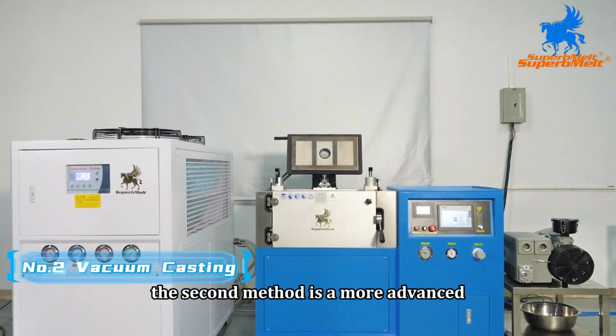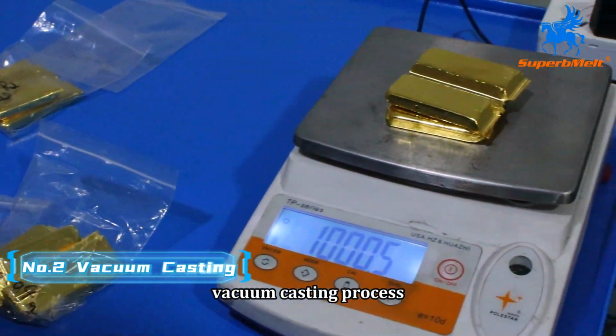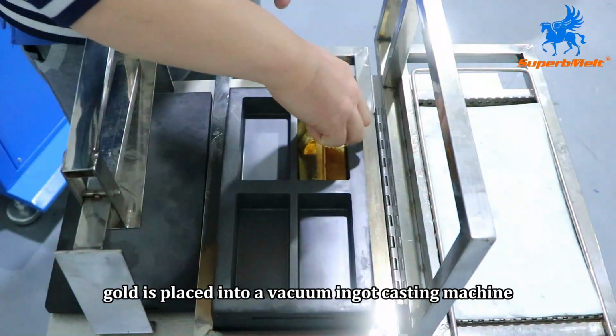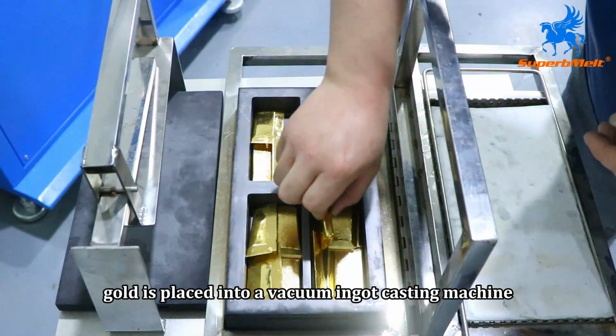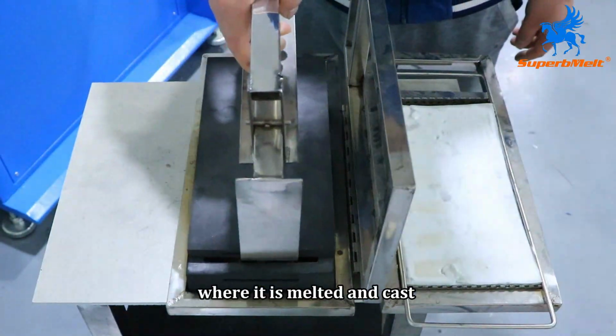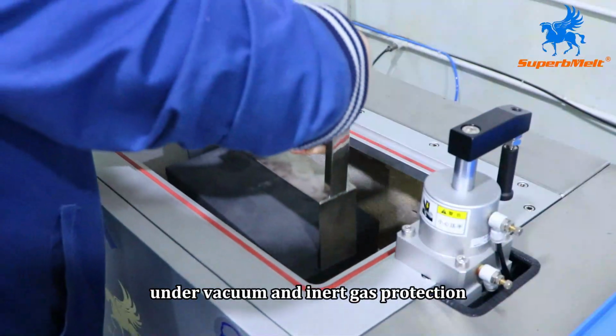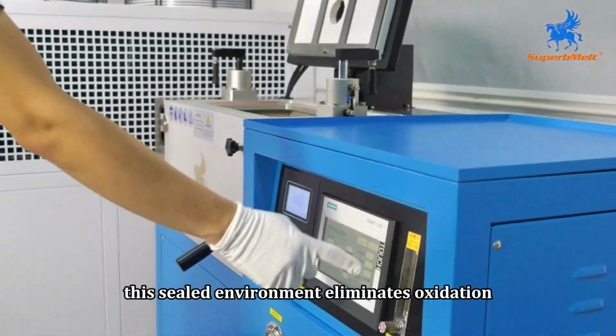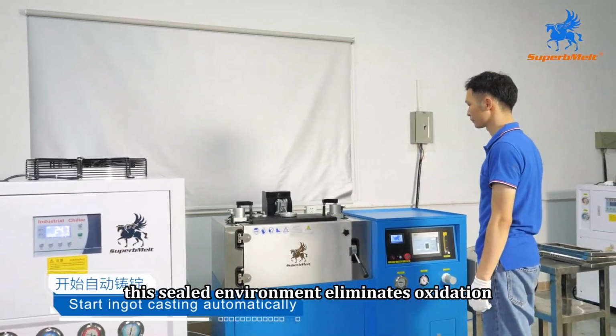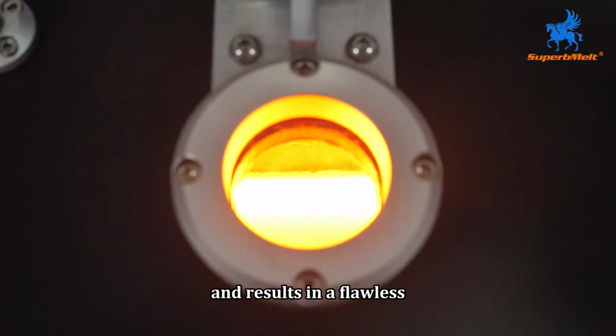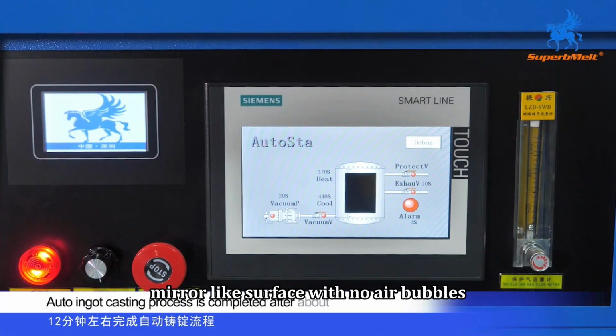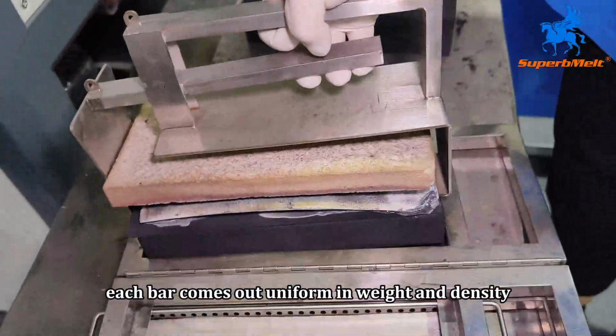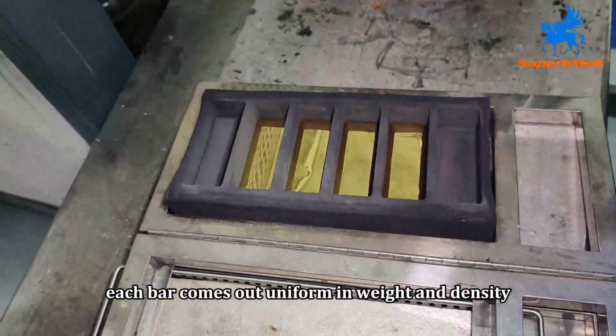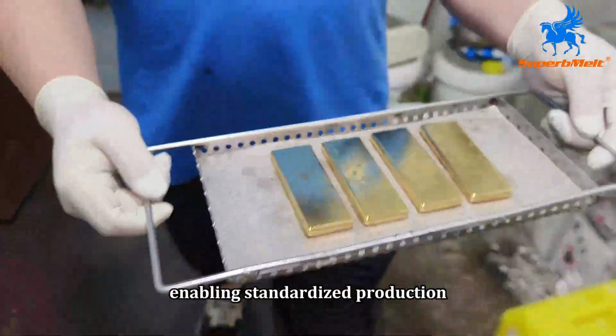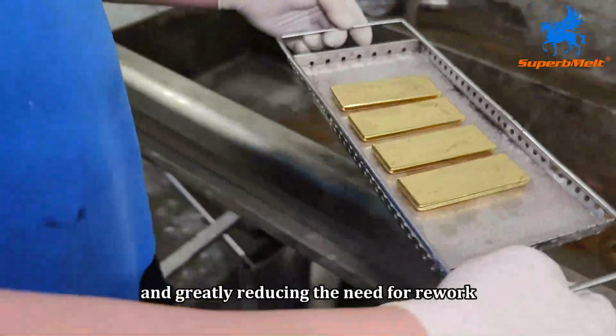The second method is a more advanced vacuum casting process. In this method, gold is placed into a vacuum ingot casting machine, where it is melted and cast under vacuum and inert gas protection. This sealed environment eliminates oxidation and weight loss and results in a flawless, mirror-like surface with no air bubbles. Each bar comes out uniform in weight and density, enabling standardized production and greatly reducing the need for rework.